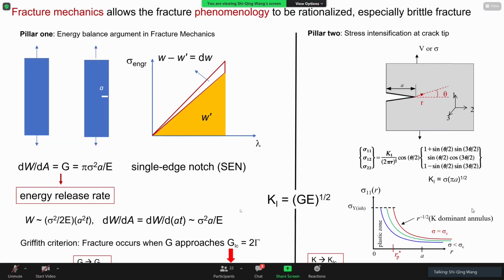Either you argue from the point of view of energy, Griffith demonstrated in the case of glasses very successfully. Basically, eventually can attribute all the fracture strengths to the fact that certain energy has to be surpassed. So then there's also the second approach, looking at the strengths at the crack tip. But since the crack tip has stress divergence, one has to introduce remedy by saying that there is a plastic zone. At the end of the day, when you go to textbook, you read fracture occurs when G reaches GC, or fracture occurs when K reaches KC. In the case of KC, we really don't know what determines KC, but luckily we know that K is related to G, therefore everything falls back to how to compute for G.